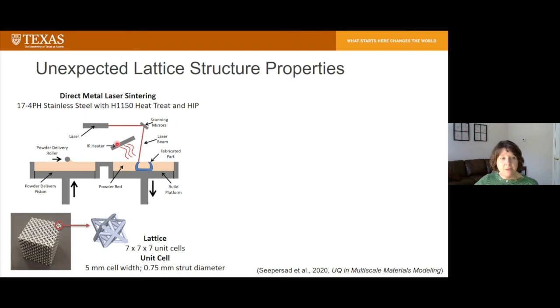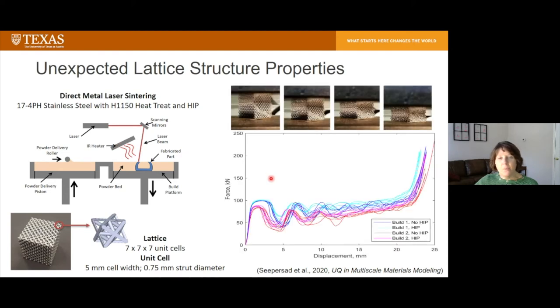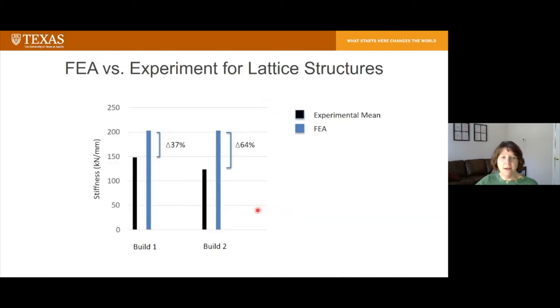We fabricated them using direct metal laser sintering, using the same type of machine that we have in our AM center. And then we tested them. So we had batches of them in one build in the blue and another build in the pink and red. And we've tested them to full densification. One of the things you'll notice is that thankfully there's a reasonable amount of consistency within each build. There's differences across the build, which I'll talk about, but neither of them are nearly as strong as we predicted they would be. So let's talk a little bit about that.